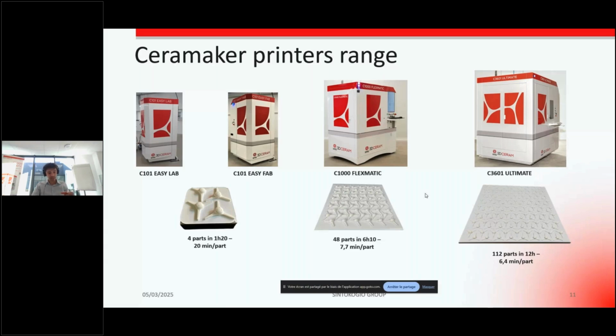For instance, if we have a look at the small alumina nozzle that you can see on this slide, this part is used in production for semiconductor application. The size of the part is roughly 5 cm by 5 cm. We can print 4 parts on the small machine, and the printing time is 20 minutes per part. If you are printing the same part on the bigger machine, you can print more than 100 parts on the printing platform, and in this case, the printing time per part is approximately 6 minutes per piece.